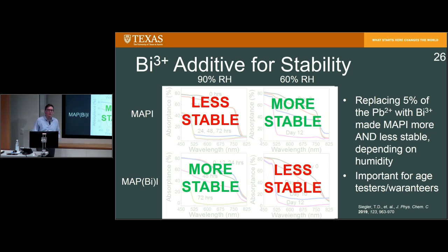And I believe that it's important for anybody who's trying to age test or warranty perovskites. The startup community is getting closer and closer to having commercial products. They're trying to get warranties on them, and they're using silicon aging tests, which involve 85 degrees Celsius, 85% relative humidity aging as a time accelerant. And I don't think that is necessarily good, given the fact that additives can have this disparate effect above and below a certain threshold, about 75 to 85% relative humidity.